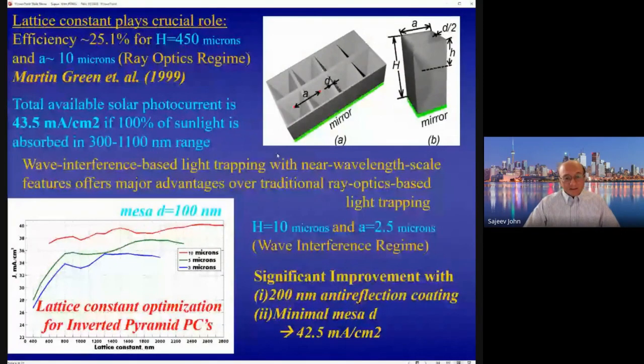And more recently, we have been studying situations where that lattice constant is much smaller and comparable to the wavelength of light, to see if we can enhance the absorption of light in much thinner structures than this enormously thick 450 micron structure. So we started out by doing simulations on these structures. The parameters involved are the height, the thickness of the silicon, the lattice spacing, and the width of the mesa, which is this parameter d.